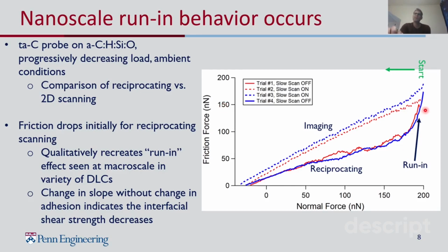The way this experiment was run was we started at a very high normal force of 200 nanonewtons. And then we progressively reduce the load every scan line until the tip eventually pulls off the surface. And what you can see in the imaging case, where every scan line is on fresh material, is that there's a linear scaling across the load range. And that linear scaling is indicative that we actually have a multi-asperity contact. And the slope of this line can be compared to a friction coefficient that you would get based on Amonton's law.